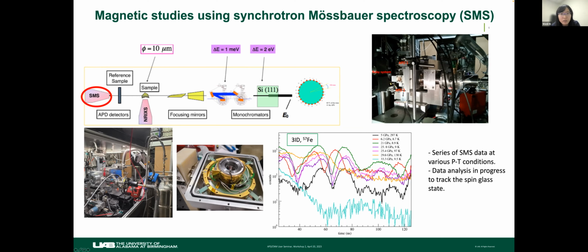In this case, early on, we were using this cryostat originally designed by Stas from DAC Tools. Because there was some malfunction on this cryostat, we quickly switched to a new cryostat, again made by Stas from DAC Tools. And we were able to cool down and took a series of data at different temperature and pressure conditions. And we found that the critical pressure at which the magnetism is suppressed happens at a higher pressure at slightly higher temperature. That's kind of counterintuitive because temperature itself acts like a pressure effect. So here we observe the suppression occurs at slightly higher pressure.